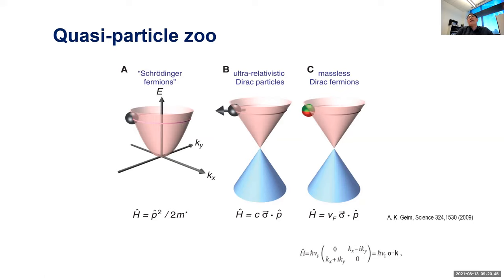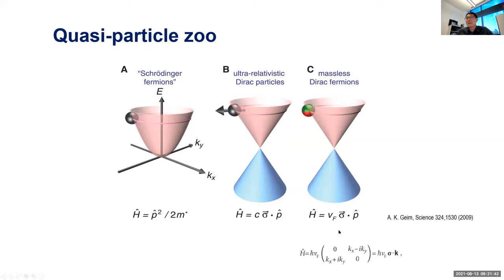In heavy-ion collisions, particles generated are ultrarelativistic with different dispersions described by the Dirac Hamiltonian: H = c(σ·p), where the energy-momentum relation is linear. In condensed matter, I don't have particles at the speed of light, but at the Fermi velocity. If the dispersion is linear, we can use Dirac equations by replacing the speed of light with Fermi velocity: H = v_F(σ·p), a pseudo-spin matrix times momentum. We know this works — graphene at the nodal directions has linear dispersion. And chiral semimetals are semimetals with zero gap and linear dispersion, discovered within the last 10 years.